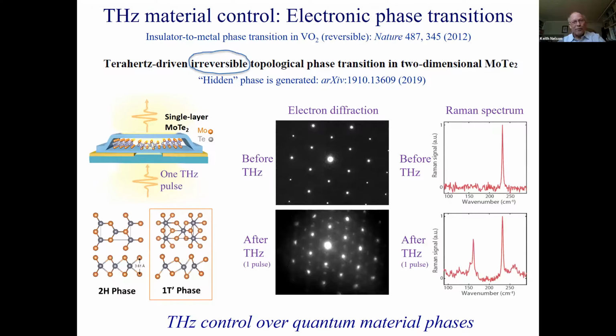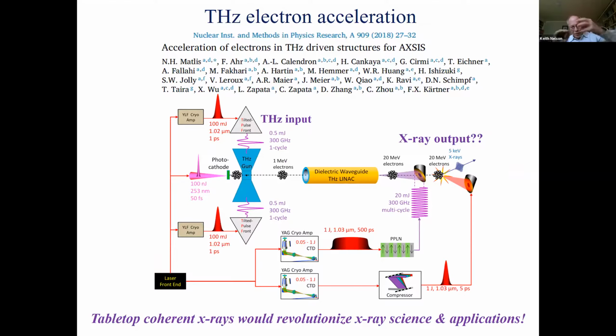One more example of what terahertz fields do with electrons: they can actually induce phase transitions, change a material's structure, crystalline structure, and electrical properties. So for example, insulator-metal phase transitions can be induced this way, or in this case, with single layer molybdenum ditelluride, one terahertz pulse actually fabricates a new crystalline structure. You can see that in the electron diffraction pattern. It's permanently changed after just one pulse, and so is the Raman spectrum that shows the vibrations of this new crystal lattice.